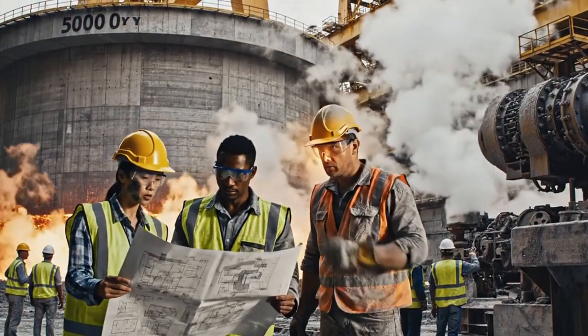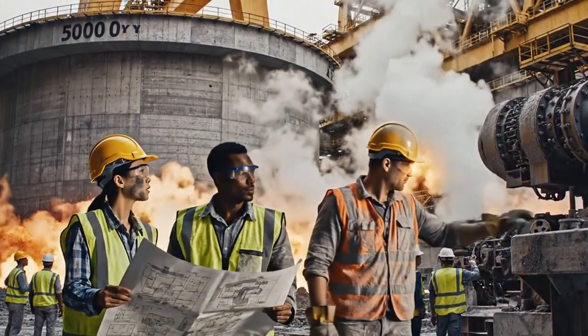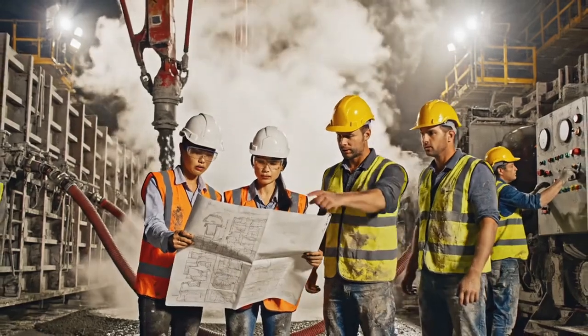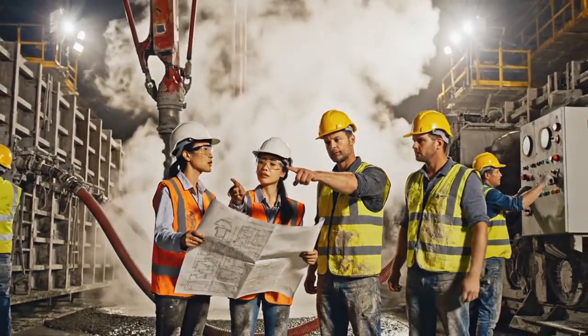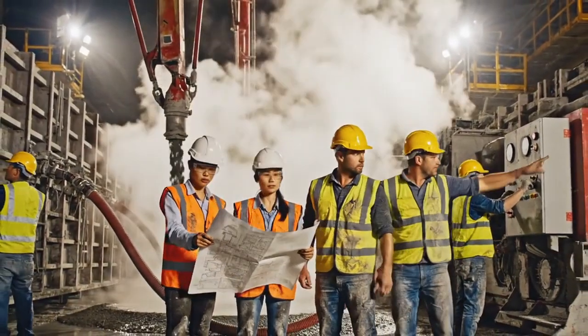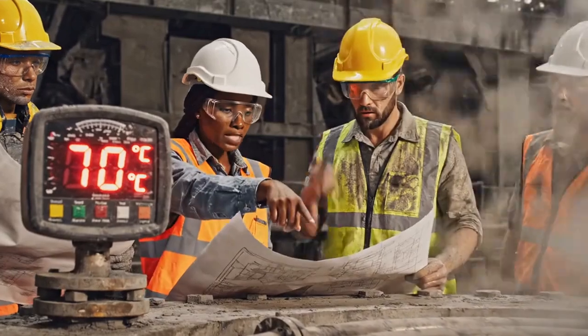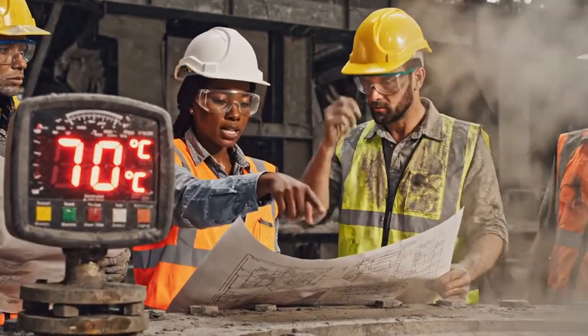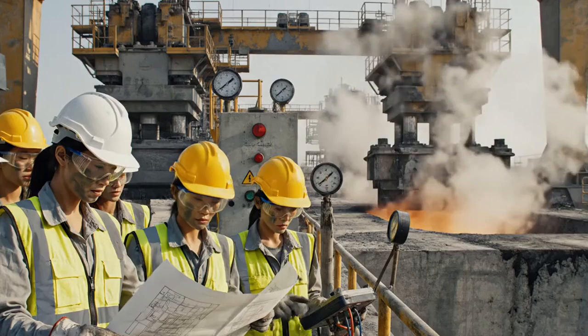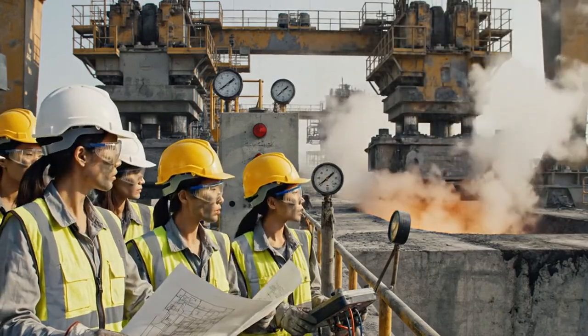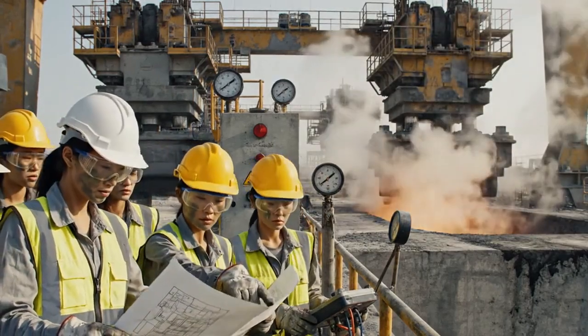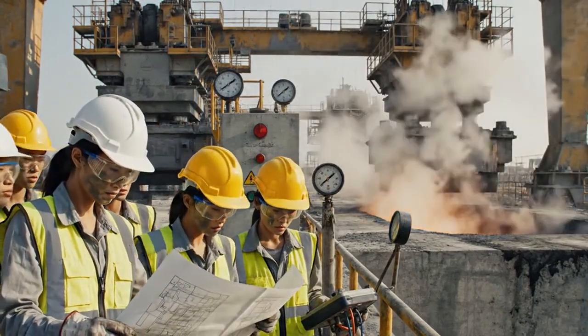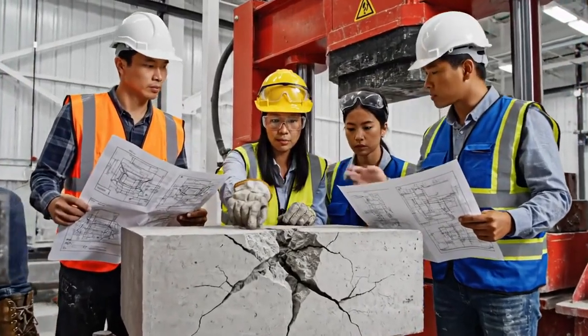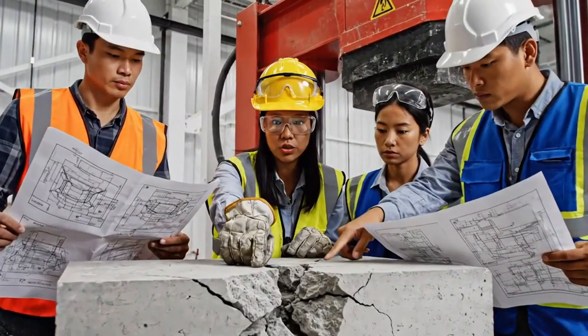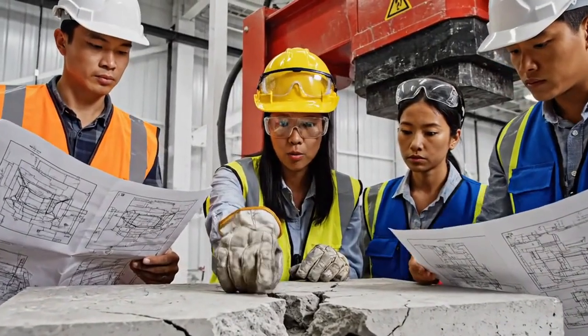The curing process of this 50,000-ton concrete core presents a massive thermodynamic challenge. The hydration of cement is a highly exothermic reaction. In a structural pour of this magnitude, the internal heat generated can easily exceed 70 degrees Celsius. If the temperature differential between the core and the exterior surface surpasses 20 degrees Celsius, thermal cracking becomes inevitable, severely compromising the structural integrity and water tightness of the module.